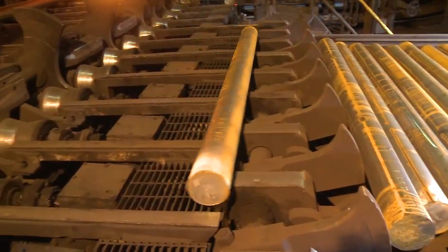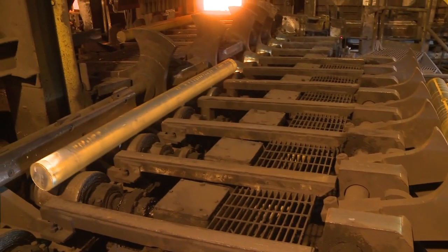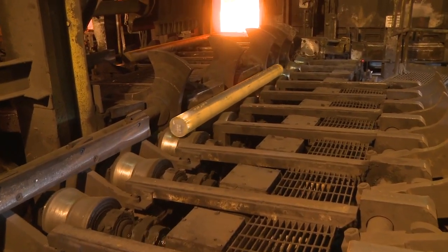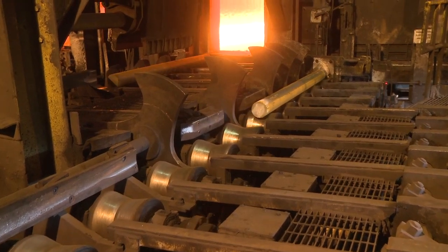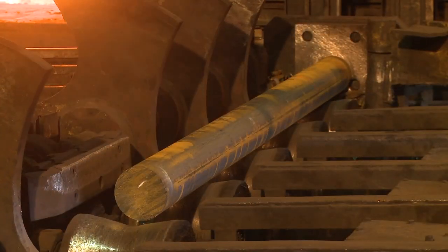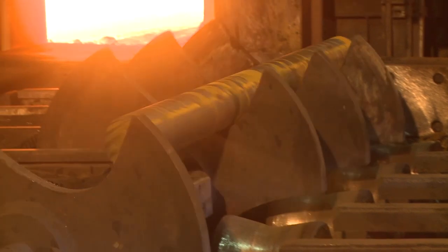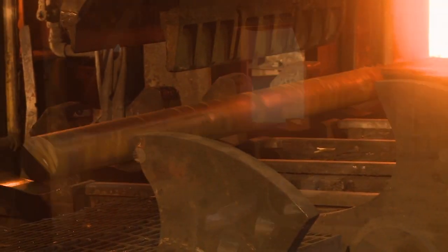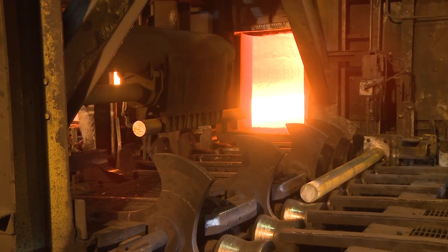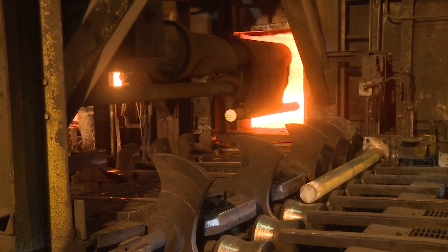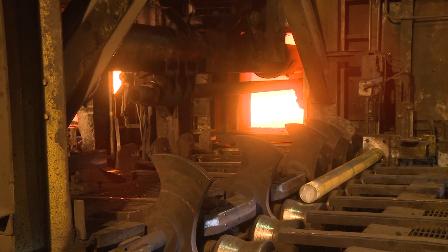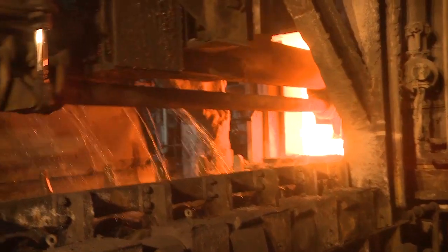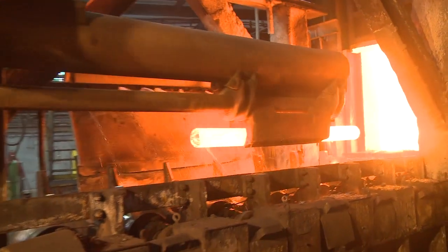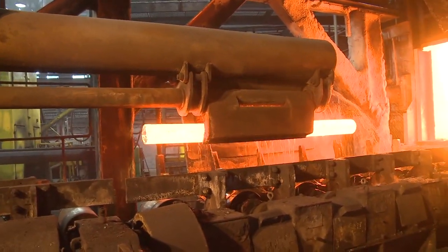Before we can convert these billets to seamless mechanical tubing, a rotary hearth furnace must heat them up at temperatures ranging from 2,000 to 2,300 degrees Fahrenheit. The rotary furnace has 5 different heating zones and allows us to heat different orders to different temperatures, depending on each grade of steel. We control the furnace by computer software that regulates heating requirements based on the billet size. Once we heat the billet to the proper temperature, we discharge it from the furnace and convey it to the center punch.